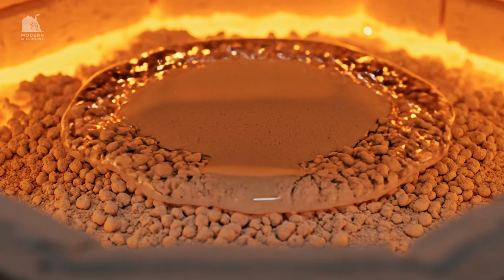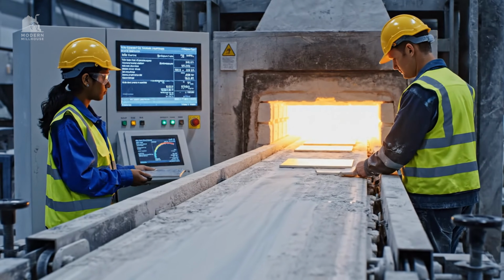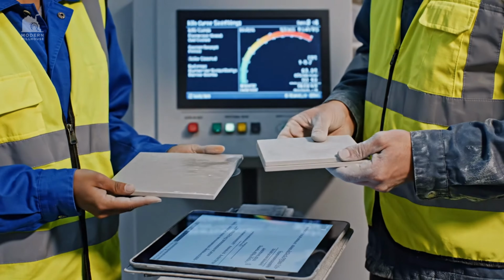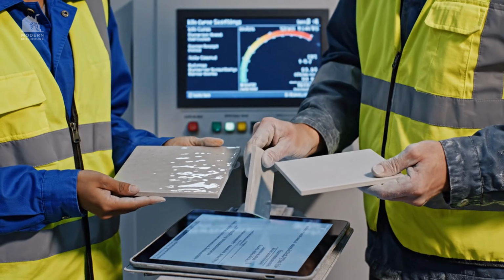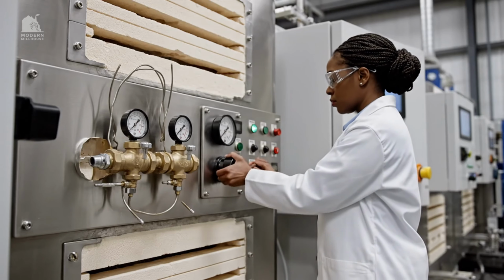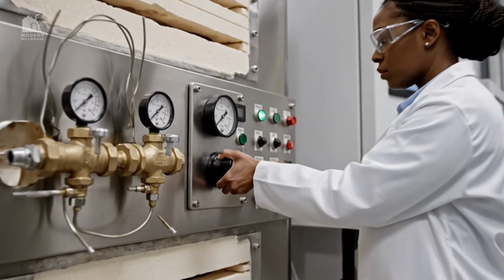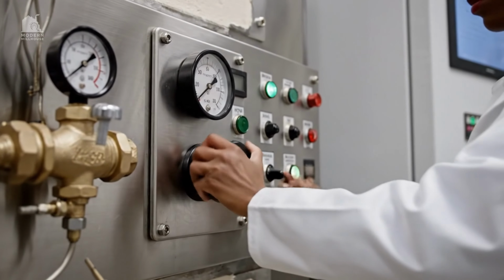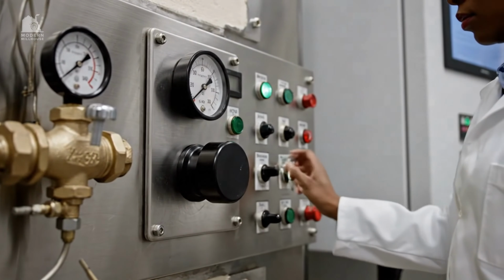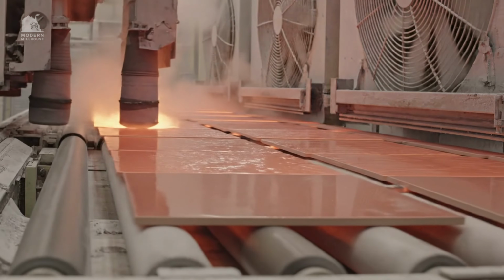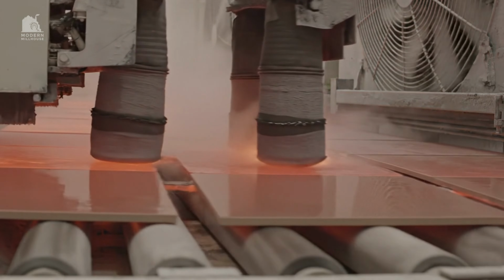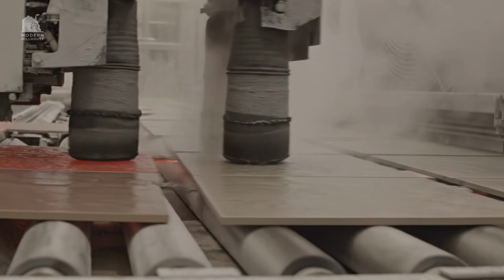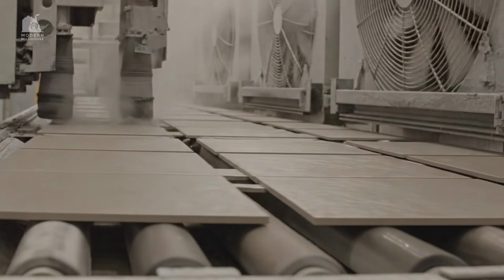Kiln curves are documented like recipes. Operators track belt speed, burner settings, and zone temperatures, then compare results against reference tiles. If a glaze shows pinholes, they may slow the ramp or extend a soak so gases escape before the glaze seals. If tiles warp, they may adjust temperature uniformity, roller support, or body particle distribution upstream.